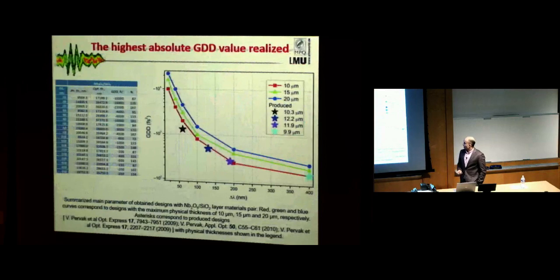And the last curve which I want to show you: always when we produce a design, it's a trade-off. When we have very short pulses, we have a very large bandwidth, and we can provide just a certain group delay dispersion, like minus 50 femtosecond squared. If we reduce our bandwidth, we go for longer pulses, and we speak about 100 femtosecond pulses or whatever, we can produce much larger dispersion.